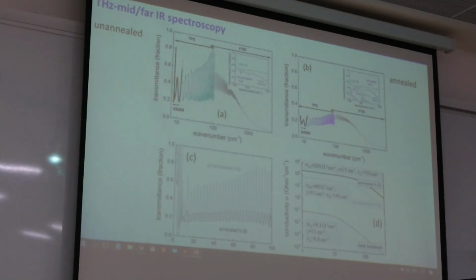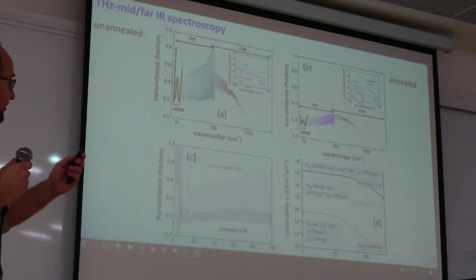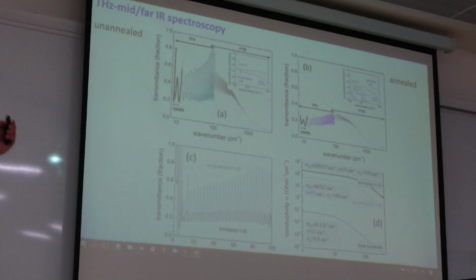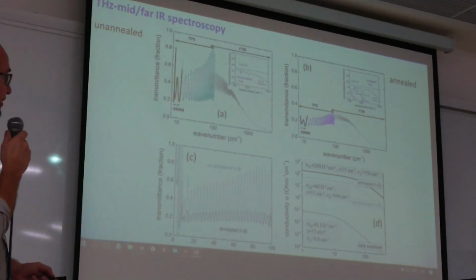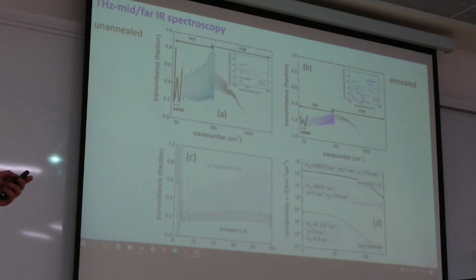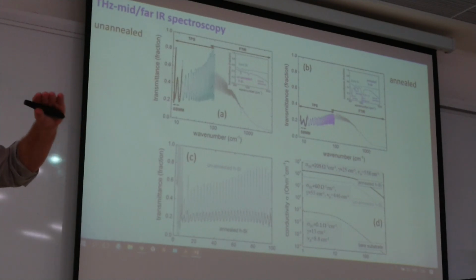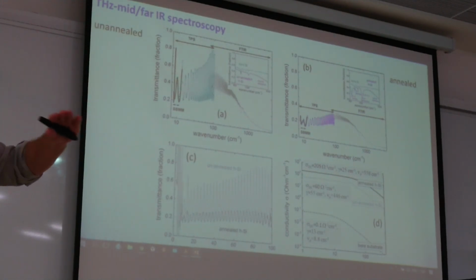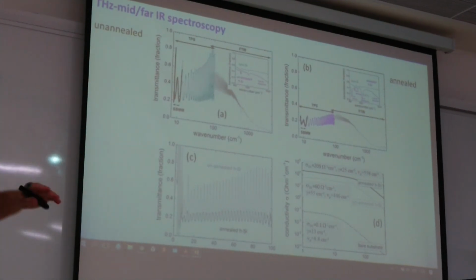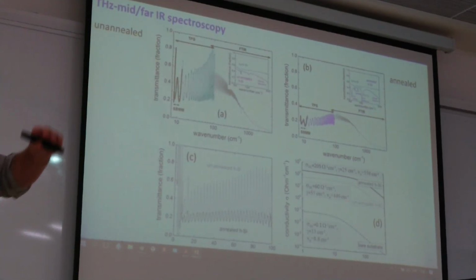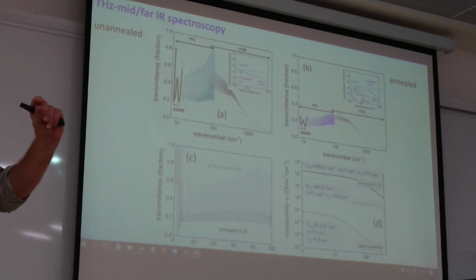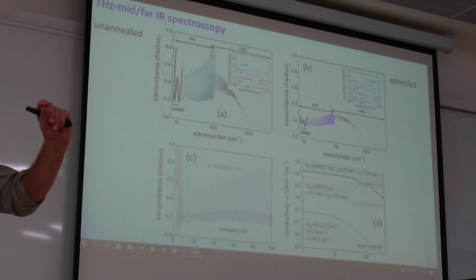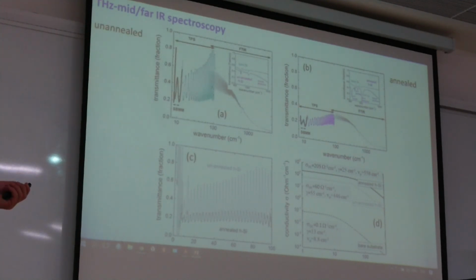Okay. And finally, we have done terahertz and far infrared spectroscopy on these materials: on annealed hyperdoped silicon, and unannealed one. And we see that since the silicon wafer has two polished faces, some wavelengths can resonate inside this wafer if the wavelength is comparable to the wafer thickness. And as a result, you can see these kind of oscillations.